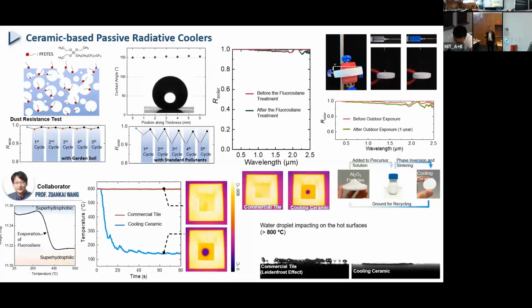Most importantly, we put our cooling ceramic outdoors naturally for over 1 year, and then we measured the solar reflectivity. You can see the green line, the solar reflectivity, dropped lower than the original before the outdoor exposure, but the overall drop is only about 1.5%. So it can still keep around 98%. This again proves that the metal oxide material has a very strong effect against the degradation from UV light.